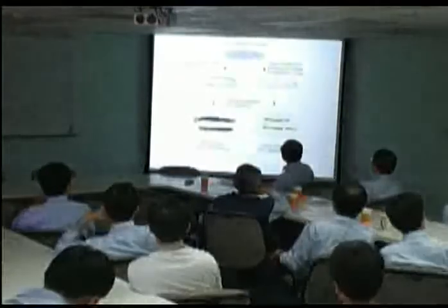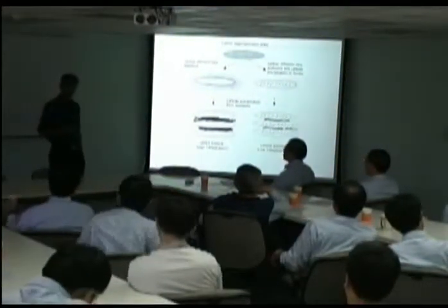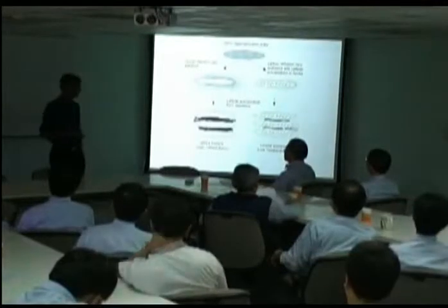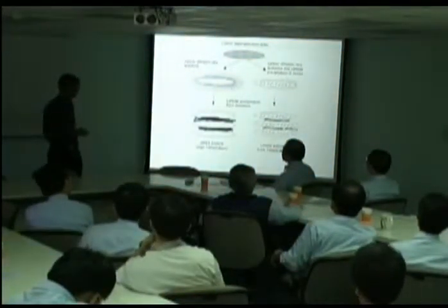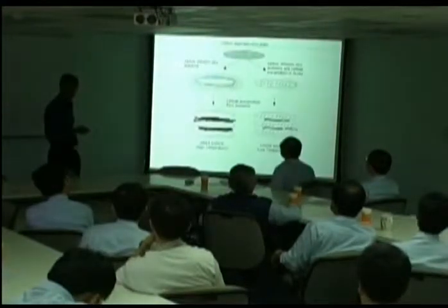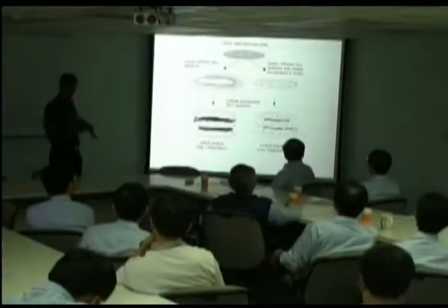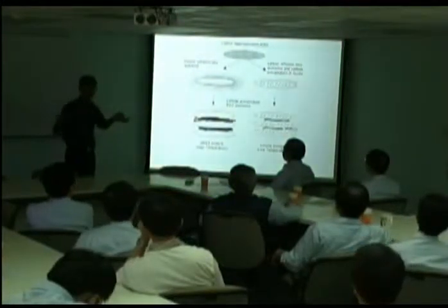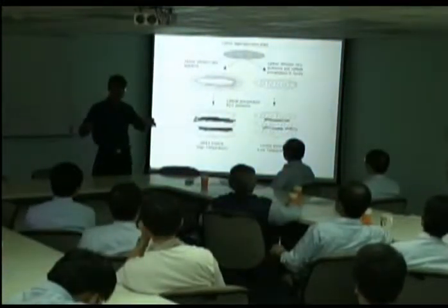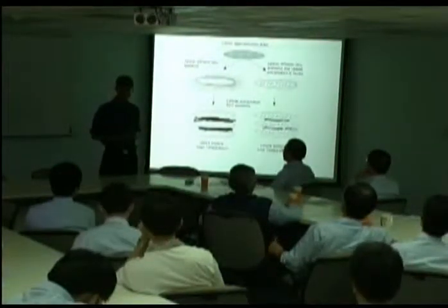Now, of course, it also naturally explains the transition from upper to lower bainite. When we get upper bainite, we are at a relatively high temperature, so the carbon can escape fast into the austenite, and then we get precipitation from there. Whereas in this case, it's a lower temperature, so we have an opportunity to precipitate inside the ferrite, just like tempering of martensite, and then get cementite in between the plates.